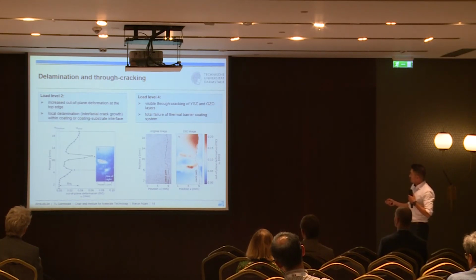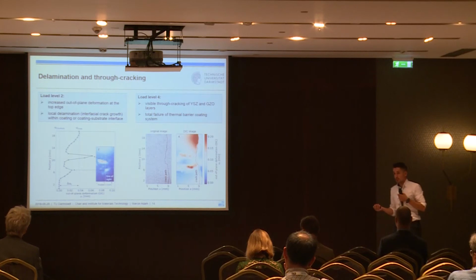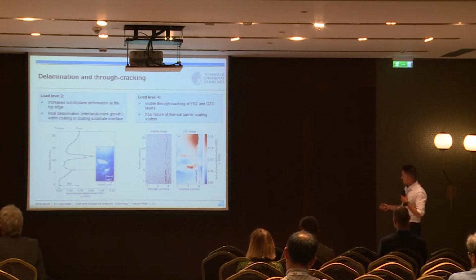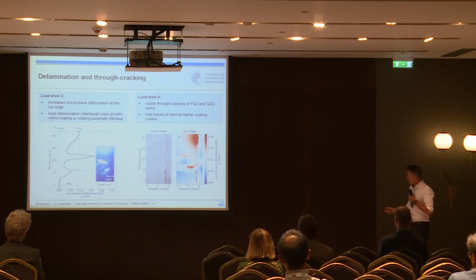Last but not least, load level number 4 was the load level where the highest acoustic emission energy level has been reached. And we clearly see here the original image and the DIC evaluated image, also the out-of-plane deformation, and we clearly see this crack path in the original image. We can see the crack path very well in the DIC image, and as mentioned before, we have these red spots of gadolinium zirconate buckling, and also the widespread area of interfacial crack growth or delamination starting from the top edge.